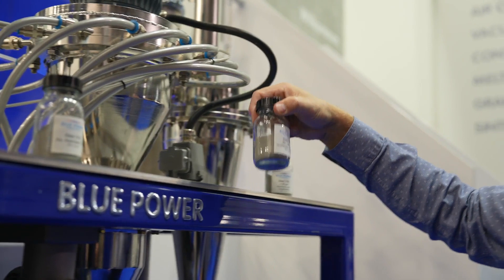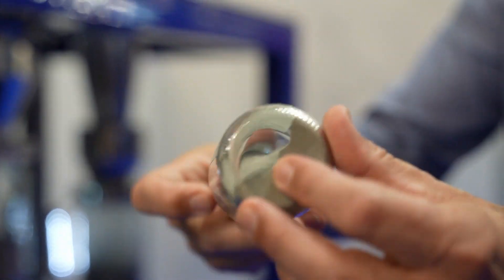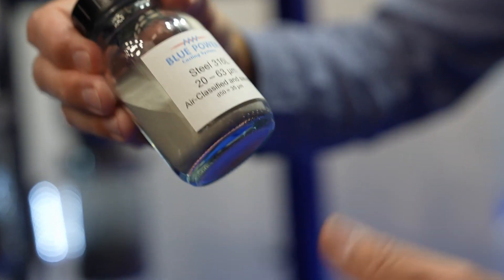What we can obtain in this receiver here is nicely flowing powder, and this is again thanks to removing the fine dust from the atomized batch. In this air classification process, you have the opportunity to continuously shift the cut point from basically 3 micron up to 100 micron or above. So that's a very convenient tool to fine-tune properties and the fraction of the powder that you are going to use in the printing process.